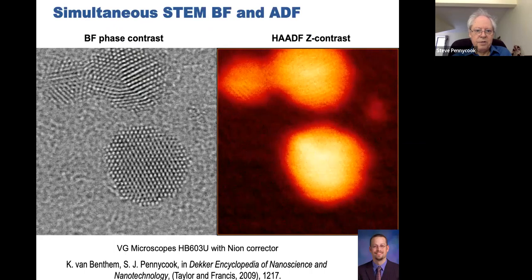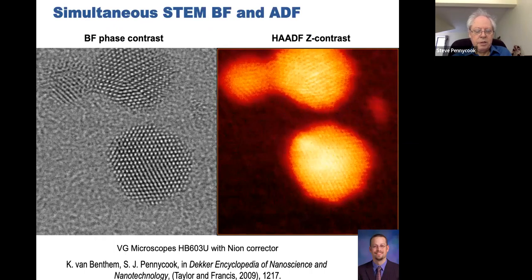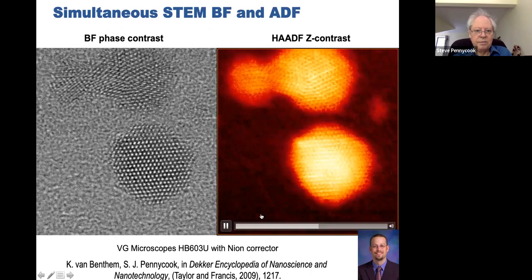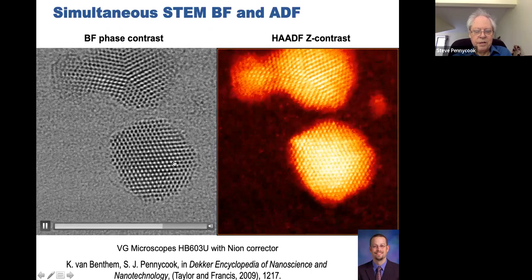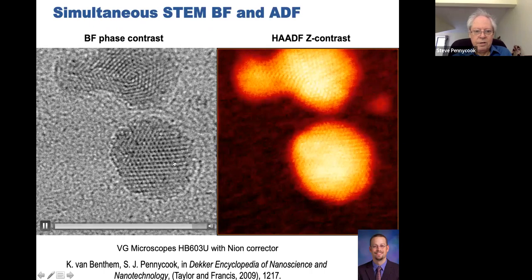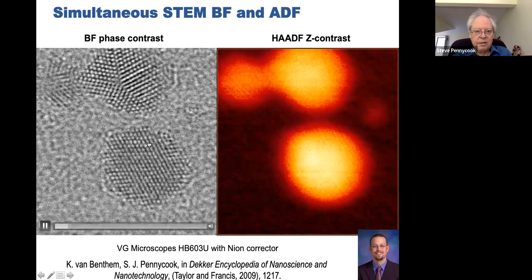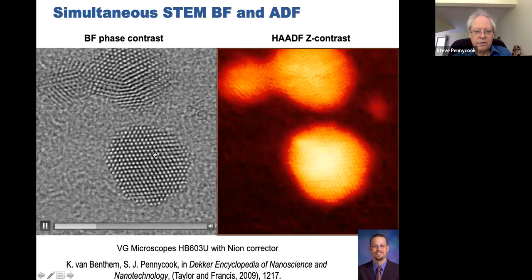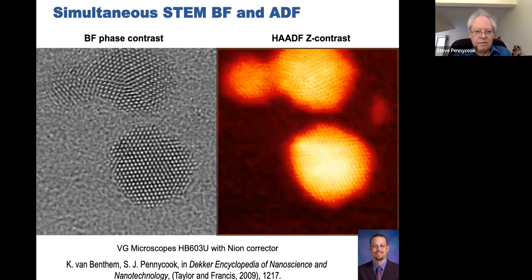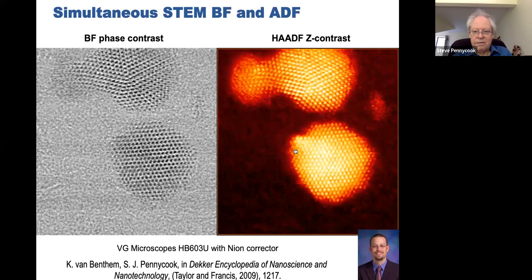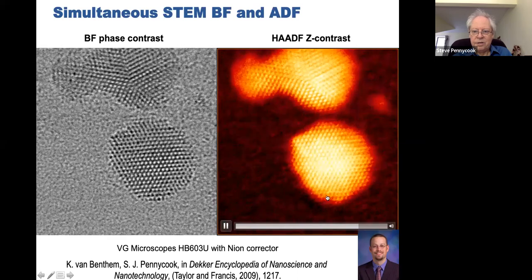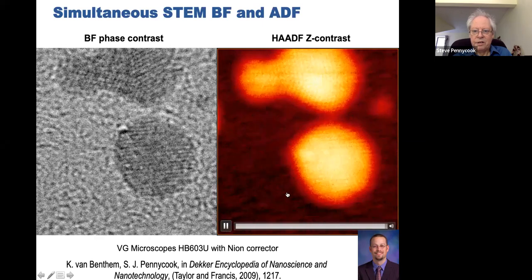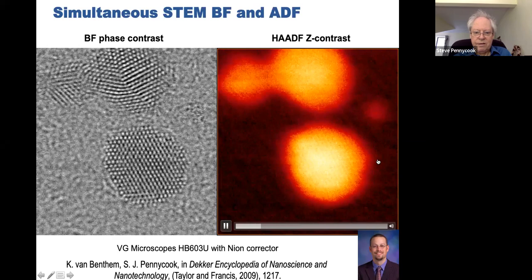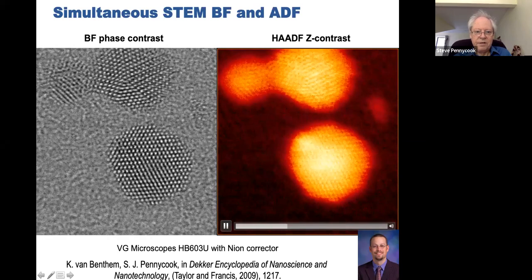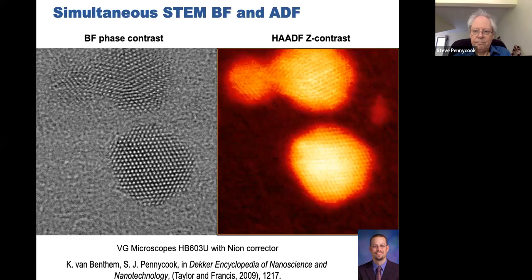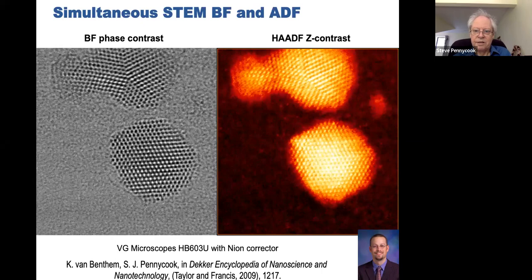Well, the other thing we found was that the bright field image, we were able to open up that collector aperture and get really good signal, simultaneously. And if you watch, when this one, let's play that through again, when this one goes through its contrast reversal around here, this Z contrast image, this is when all the single atoms around the edge are beautifully in focus. So very nice to have the phase contrast simultaneously with the Z contrast. There it goes again.